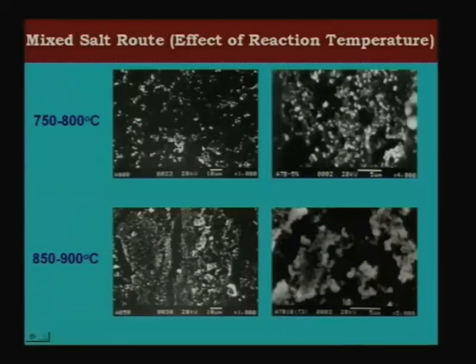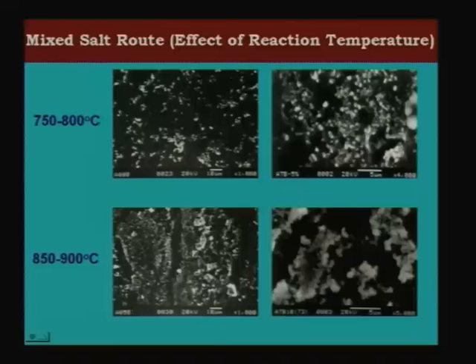So one can also study the effect of temperature. At higher temperature there is a problem. The problem is, as I told you before, KBF4 has a tendency to dissociate and form BF3 gas, and this tendency to dissociate increases with increase in temperature. So if you go to a higher temperature, 850 to 900 degrees centigrade, you end up with fewer particles, and most of those particles will be Al3Ti particles, because most of the boron has already vanished. So you do not have the boron left to react with the liquid metal to give you the TiB2 particles. So one has to control the temperature and keep the temperature down so that you have the formation of TiB2 particles alone.